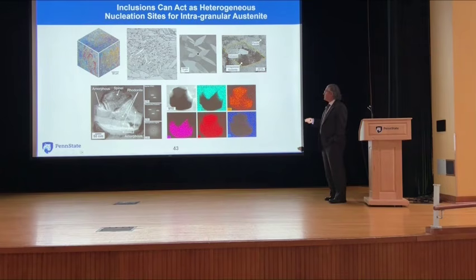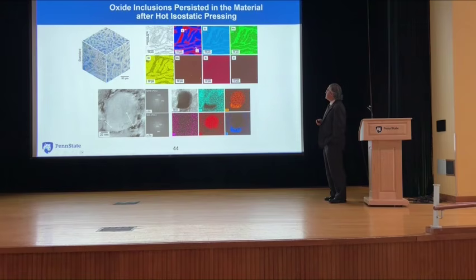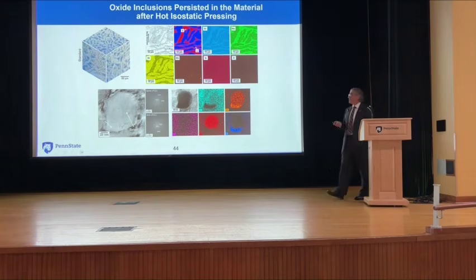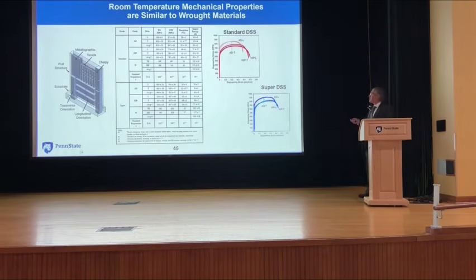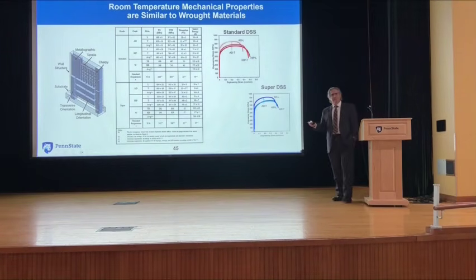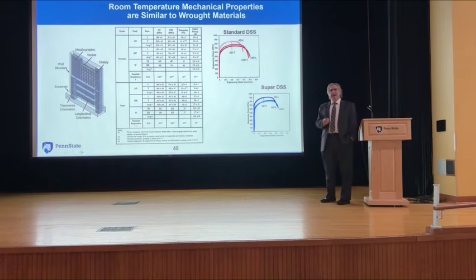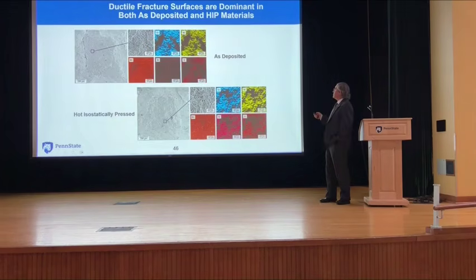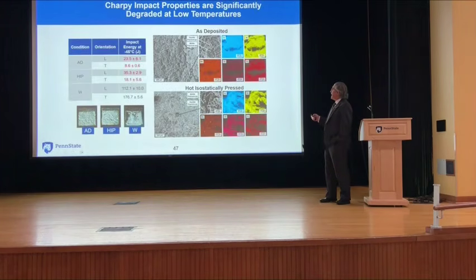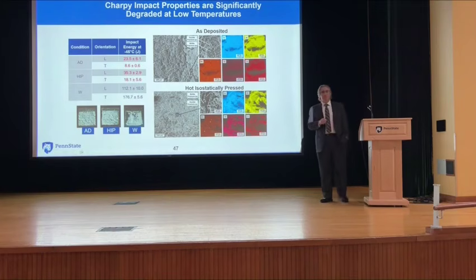You start running into an evolution of this inclusion, and sooner or later it will show up all over the place as you start looking at your additively manufactured component. The issue becomes, and there's some thought there, is, hey, there are oxide inclusions, there's oxide dispersion strengthening, right? When we start looking at really static mechanical properties, that's fine until we do things at low temperatures.